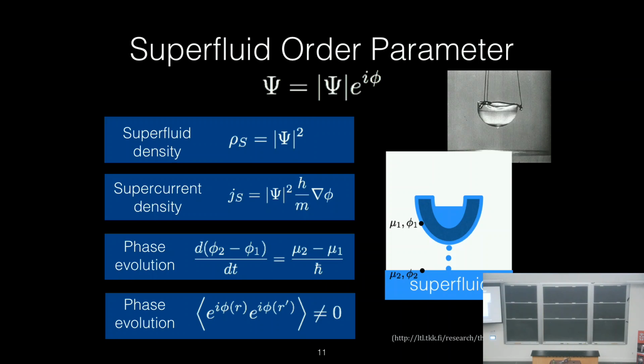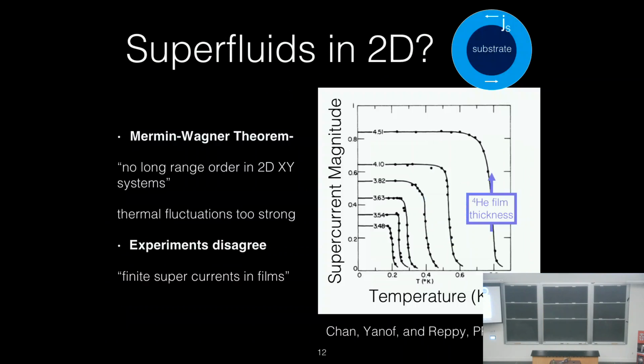That phase can fluctuate. It can change in time. So imagine here are two places. One's in this fluid and one's up here. This has a chemical potential of mu1. This has a chemical potential of mu2. There's a driving force that tries to get this to move from here to here because of the chemical potential difference. Quantum mechanically, that means that the phase difference between those two places is going to evolve in time. I want you to pay attention to this: phase differences that change in time and the superfluid current density. Currents turn into voltages when you have charges. Currents, voltages, those give you resistances. That's what you measure in an experiment when you measure resistances. Okay, so can you have superfluids in 2 dimensions? This was a big deal question for a while.